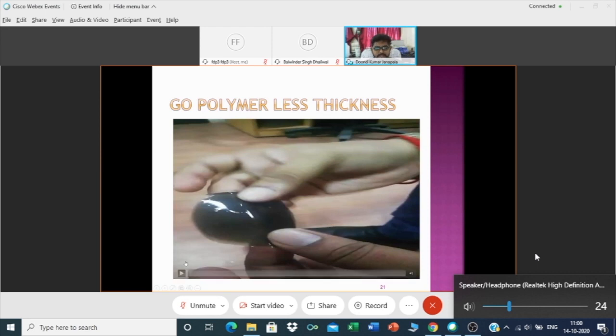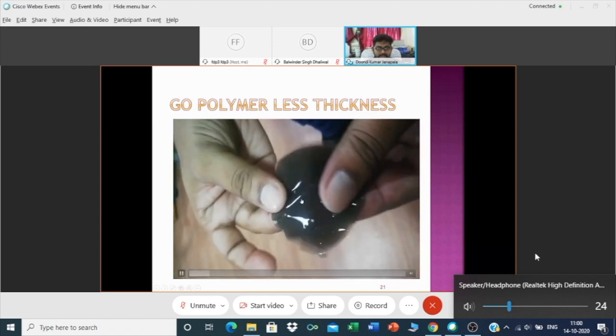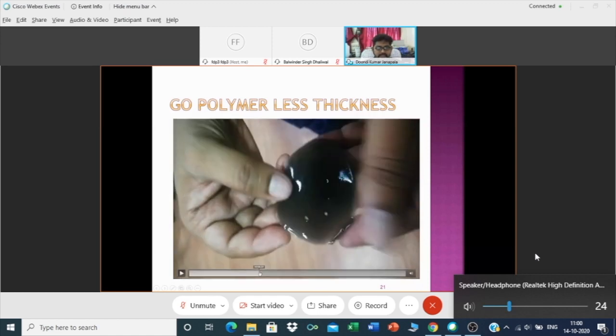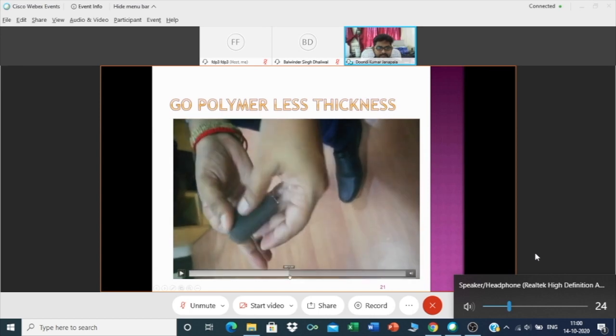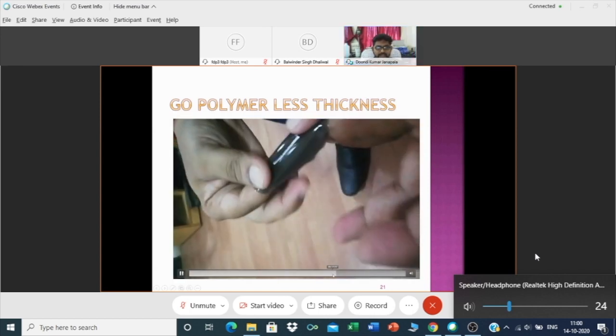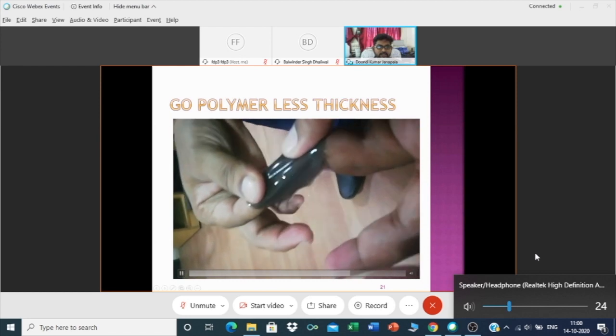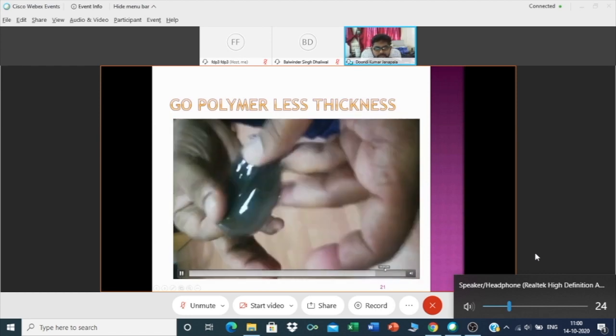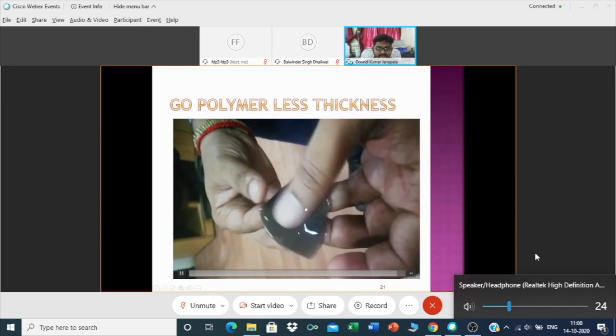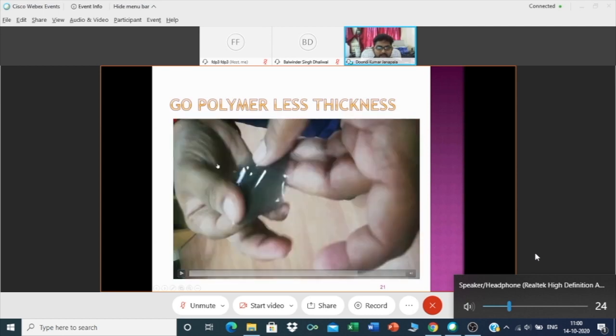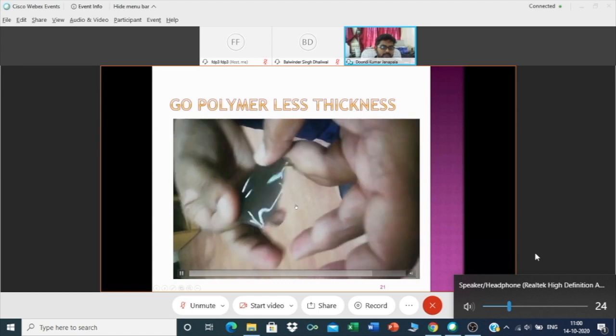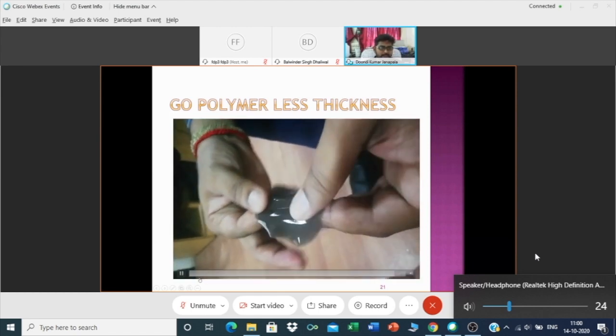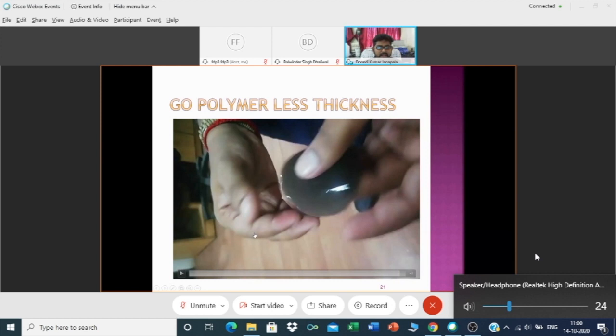This is one functionalized graphene prepared by my Professor Jabbar Singh sir, which I used. Here you can see the polymer is very thin, and it is very good in elasticity. You can see very good elastic stability. This is another one we worked on, but when I mix it, a couple of problems I am facing: some bubbles are forming while baking, even though there are no bubbles when I put it inside. This is probably due to maintaining the pH quantity when I mix the solvent. So I am trying to adjust that point now.